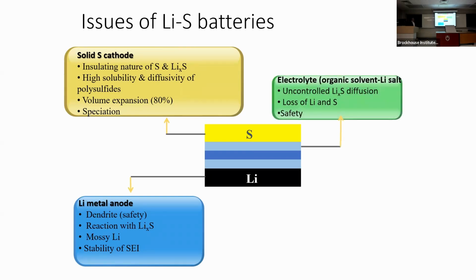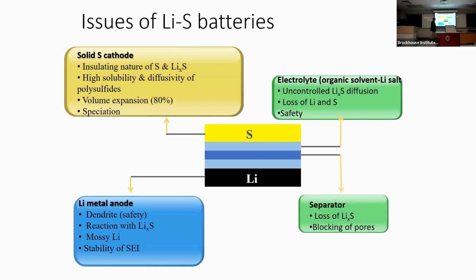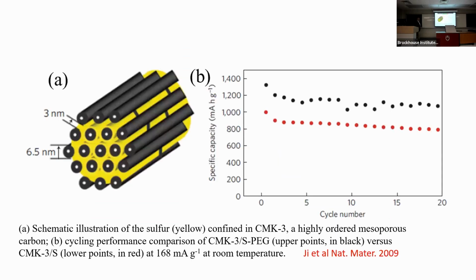Okay. Now the electrolyte organic solvent, I mentioned that, of course, you can change the nature of the electrolyte to control the diffusion rate and the viscosity, etc. But however, as a result of those reactions, you have a loss. And the electrolyte itself can contribute to safety by actually getting hot and vaporizing and creating various gases. And there is a separator in all of these materials, which actually tries to keep the anode and cathodes away from each other. If that separator became a solid electrolyte by itself, that will have a huge impact on this battery. Now let me give you